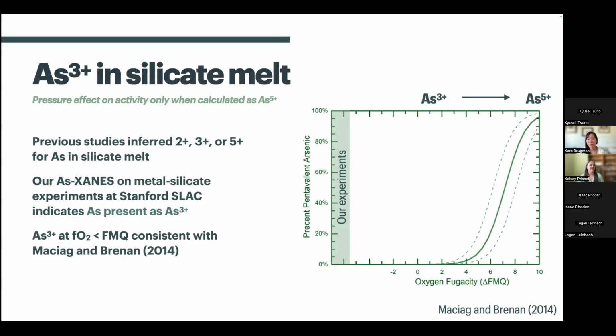And there's a question as to whether there's a 2+, 3+, or 5+ oxidation state for arsenic in these systems. Other papers have hypothesized those different oxidation states. So what we did at SLAC was to directly analyze, with arsenic XANES, the oxidation state of the arsenic in our samples. What we found was that it was all arsenic 3+. There's a nice study that looks at arsenic in silicate melts by Maciag and Brenan that found the transition between arsenic 3+ and arsenic 5+, and it's at way higher oxygen fugacities than what we're at. So if anything, it would be starting to get to lower oxidation states for arsenic that are lower than 3+. But we found all 3+ in our samples.